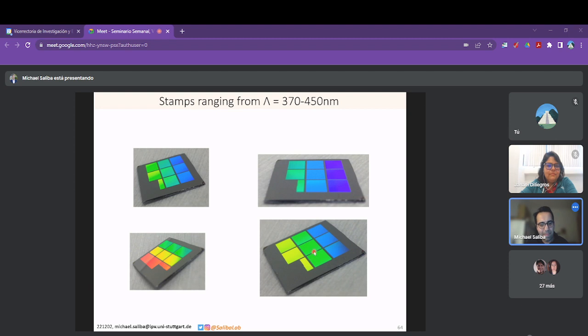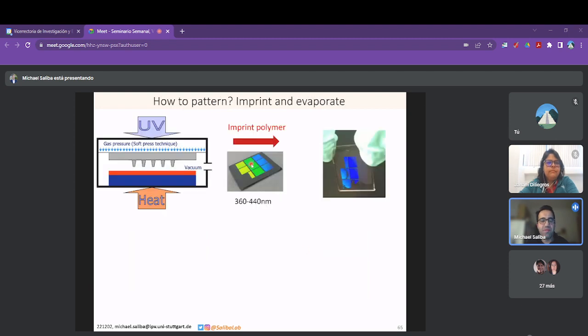And so we used the stamp and we put it on a polymer with nano imprinting. So this is the first nano imprinted sample we saw. Still not very perfect, but it worked nicely. You can see the interference fringes.